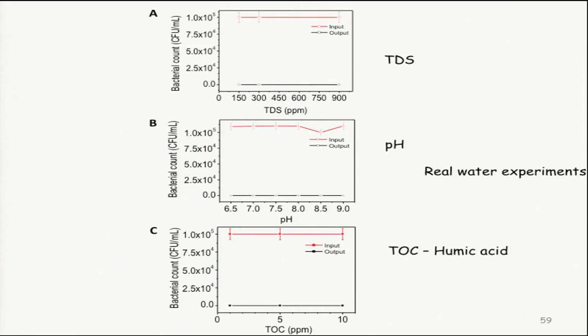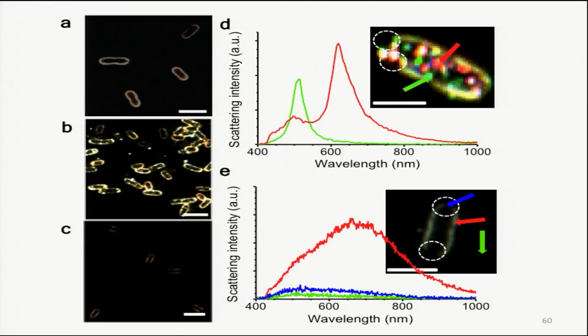At this concentration, which is below the permissible limits, you can destroy these living bacteria to dead bacteria. You can kill them. And this works, of course, at high TDS. Even at high TDS as present in our waters, in IIT Madras, we have TDS of 800 oftentimes, or even 1200. And that is the input water, and it containing bacteria, and it can be brought down. And this kind of pH you may have, you can bring this concentration of bacteria down. This may be the humic acid concentration or total organic carbon present, you can bring even in that concentration, you can bring bacterial concentration down.